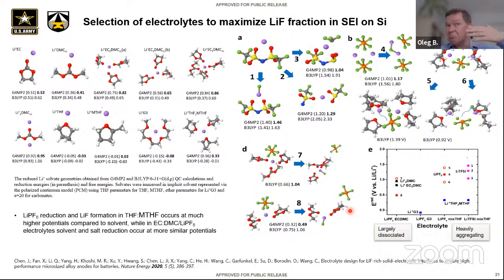So what I think happens, well, first of all, that's a time scale issue, and even in a formed SEI, it's just how to get the solvent out and compacted. SEI becomes porous, and if SEI becomes porous, like Arnaud had a nice paper on, diffusion inside of the pore of the species, convection, can bring and reform it. That's very tough. There is more and more work now where kinetic Monte Carlo is used, with very pretty pictures, something which matches cartoons.